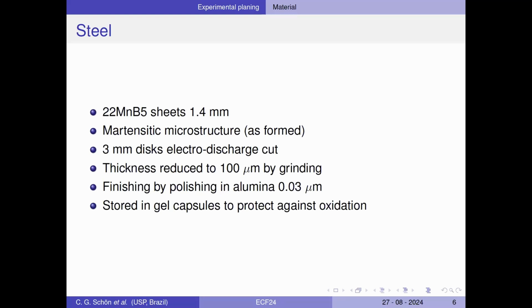What we are working with is 22MnB5 steel, a press hardening steel, which is used for the safety network in cars. It has, sadly, a martensite microstructure, and sadly because you know how messy martensite is for TEM observation. In particular because it's ferromagnetic too. It's full of dislocations, full of defects, and ferromagnetic. Everything that is hard to look at in TEM. We produce 3 mm discs for use in the TEM, reducing the thickness to 100 microns, polishing in alumina, and to protect from oxidation, we stored them in gel caps.